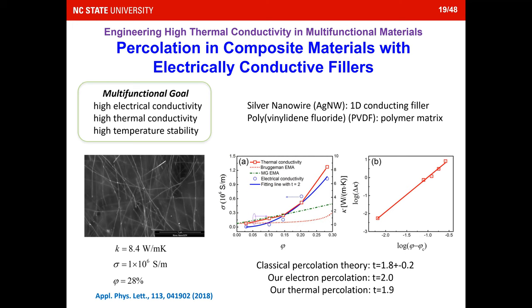And the highest one we achieved with 28% fillers is 8.4 watt per meter per Kelvin for thermal conductivity. This is already pretty high for composite materials. And then the electric conductivity is also pretty high. So we want to test whether this is the classic percolation or not. We know that if you have a percolation based on the equation I showed in the last slide, the t should be 1.8 plus minus 0.2. And based on what we have in this test, you can fit the t. We found the electrical percolation value t is 2.0 and thermal percolation is 1.9. So it's pretty much reached the percolation phenomenon.